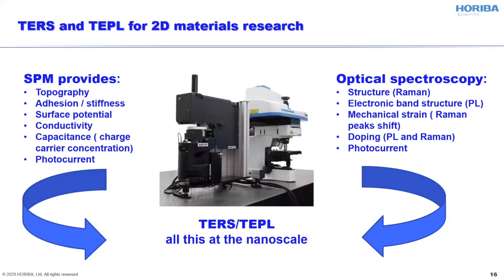Optical spectroscopy is also very popular, particularly Raman and photoluminescence spectroscopy, that can provide information about the structure of the two-dimensional semiconductor, the electronic band arrangement through the PL position and PL peak shape, and mechanical strain in the form of shift of Raman peaks in the spectra, doping, photocurrent along the sheet, and so forth.